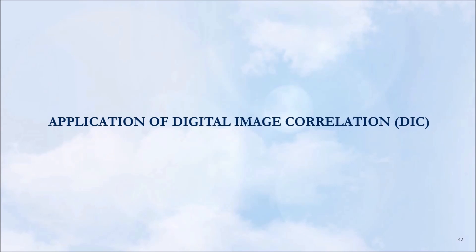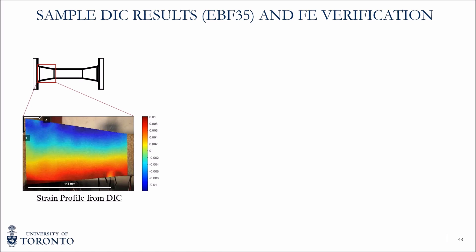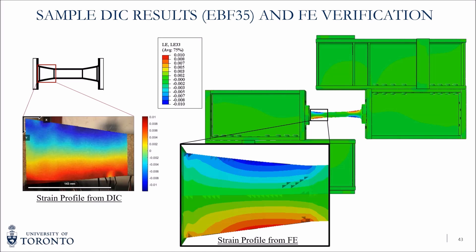We also used DIC in our component-level tests. As a quick example on EBF 35, the strain profile obtained from DIC and the strain profile from FE with the same limits match each other very well, confirming that DIC is a good method for capturing the strain profile in our experiments.